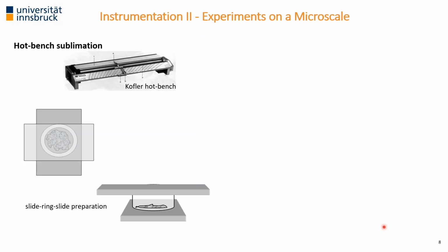But how do we quickly attempt sublimation experiments here in Innsbruck? We start with, I would say, fairly uncontrolled experiments using the Kofler hot bench, because we can control the temperature where we put our compound, but not the temperature where we sublime it to. Here we have a temperature gradient from 50 to 200 or 250 degrees centigrade. We take less than a microgram of our substance, place it on a microscope slide, put a spacer in between, and let the experiment work at different temperatures on the hot bench and check whether sublimation occurs or not. So we can quickly estimate, without reducing the pressure, of course, if a compound shows sublimation and at which temperature.